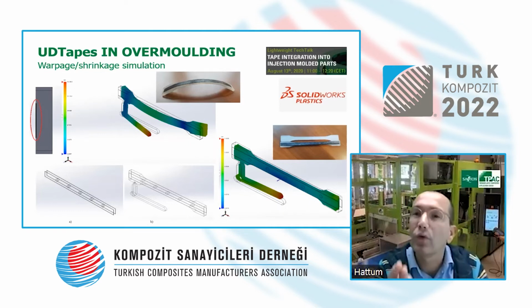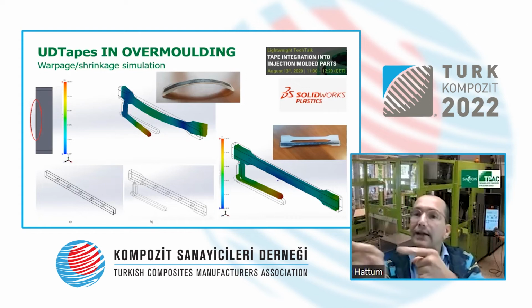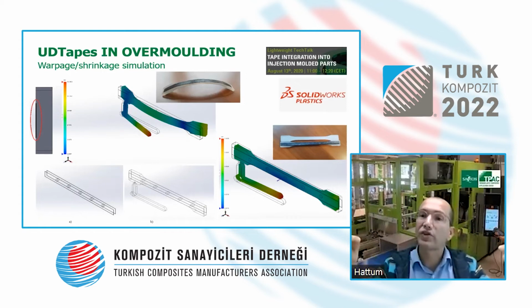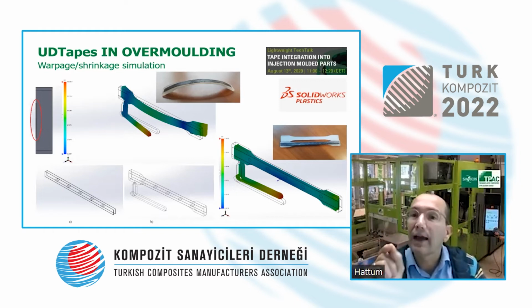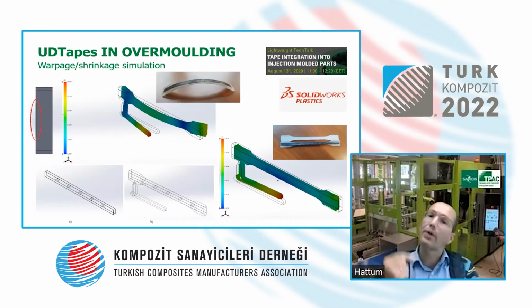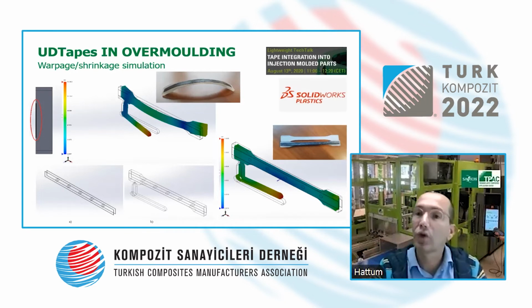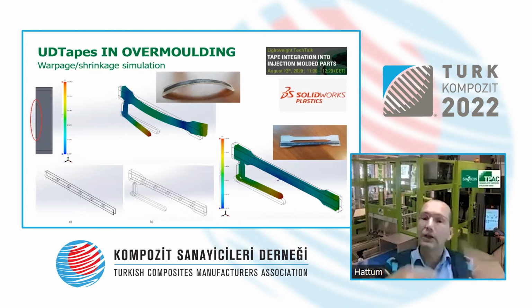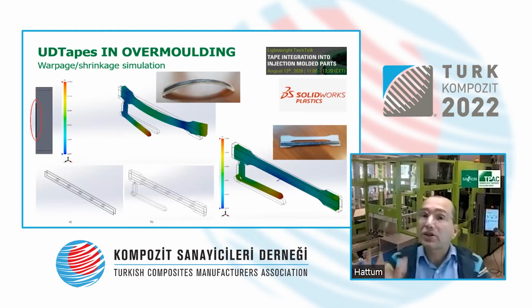And we were able to predict the kind of effect that you see in bending, but also in the shrinking of the part. If you look in close detail, I don't know if it's visible on your end of the screen, but in the picture on the right-hand side in the center, you can see one strip that is white and another tensile bar that has 2 composite strips like a sandwich in there. And if you look carefully, you can see that the polypropylene one actually shrank 2-3 millimeters more as compared to the composite reinforced one. So that's something you need to take into your equation, especially when you start.